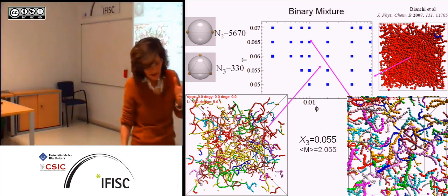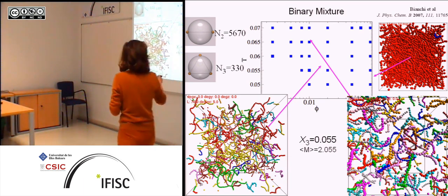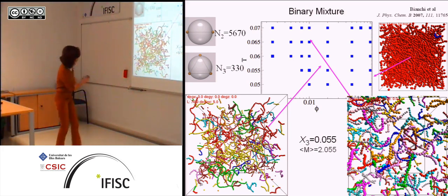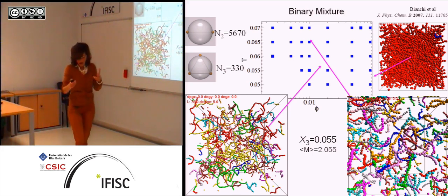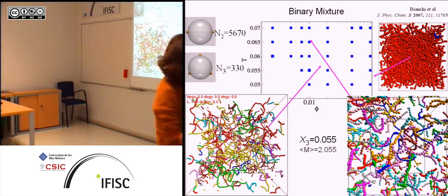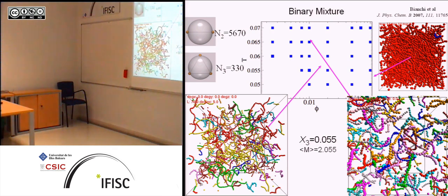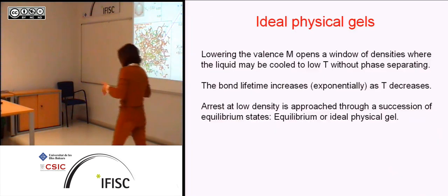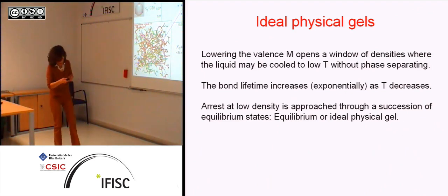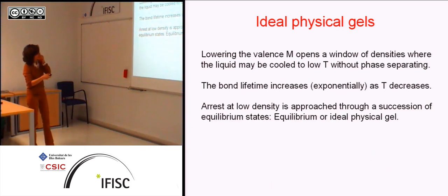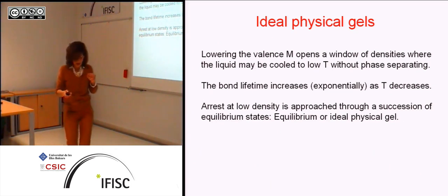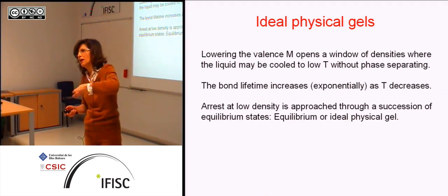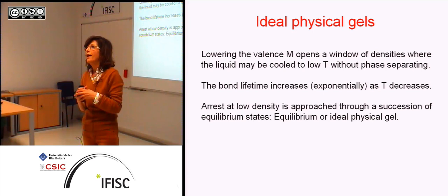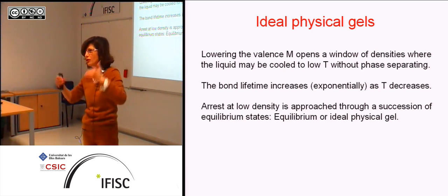And what's interesting here is that as the temperature goes down, you can see that these systems become more and more jelly-like. I mean, you see lots of chains, but these chains have junctions. And also this system is, assuming that the simulations are equilibrated, these are equilibrium polydisperse chains, which are not linear chains or not only linear chains. They may have junction defects, if you like. These junctions can have several types. So there is one way, this is the message from these sets of slides, of approaching forming these huge clusters at equilibrium in the one phase region.